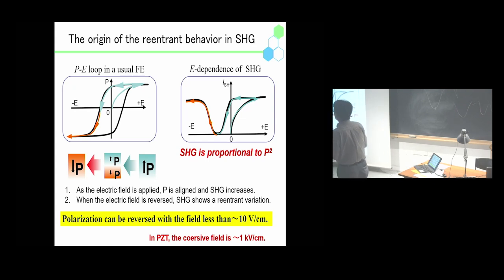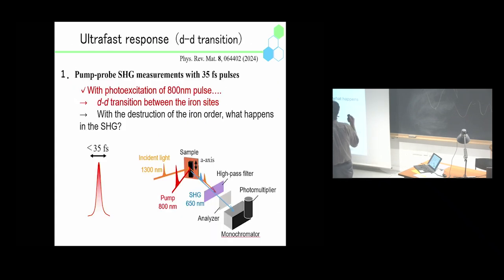Now that we have revealed that lutetium Fe2O4 and yttrium Fe2O4 are ferroelectrics, we try to observe the ultrafast response of these electronic ferroelectric materials. We performed pump and probe SHG measurements using 35 femtosecond pulses. For the pump light, we chose the 800 nanometer pulse. This excites the d-d transition between the iron sites and disturbs the charge ordering of the iron sites in the ab plane. So we investigated what happens in the SHG with the destruction of the iron order.